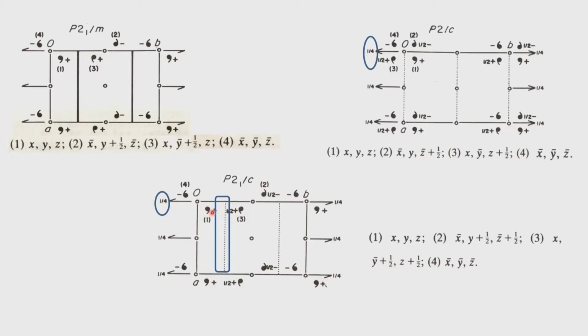So, the symmetry operation 1 will take this position 1 to a mirror position and then a half translation. This half translation will generate this point 2, which is half minus, okay, that means it is below. So, what would be the equivalent point? If there was only a 2(1) screw axis, the equivalent point would have been x bar, half plus y, z bar. Now, along the c direction we have to move by 1, the axis moves by 1/4, and therefore the position of the equivalent point moves by half, because the next operation on this particular symmetry element should take it to the next unit cell and it should overlap with 1.